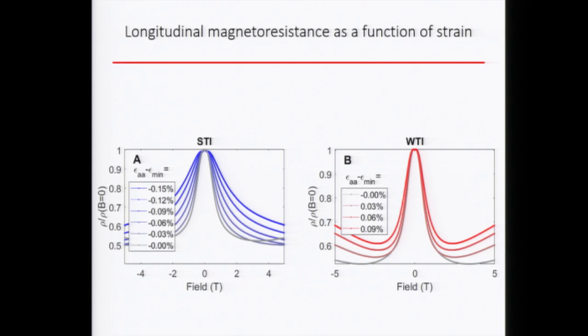If you look above 3 Tesla, 3 to 5 Tesla, for the strong case you just see the magnetoresistance keep decreasing. But for the weak, it seems you have an upturn. That also depends on how many strain states you have. There's actually a theory talking about how the longitudinal magnetoresistance could show some anomaly in the quantum limit in a topological insulator.